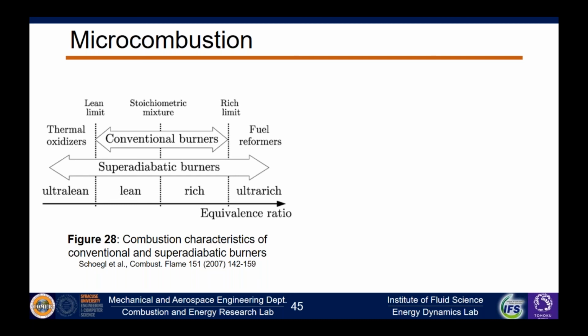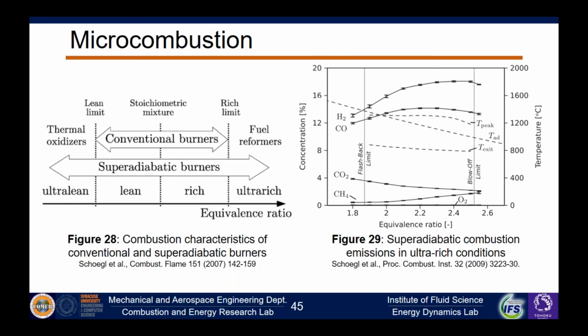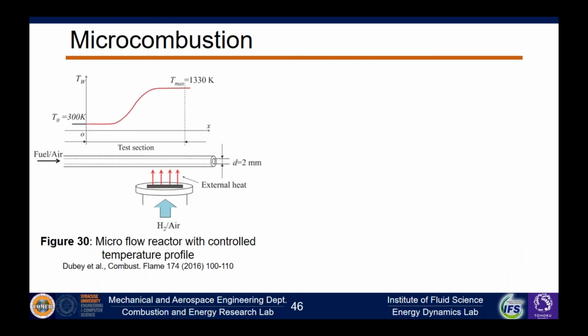Well, there's something called super adiabatic combustion, or super adiabatic burners. By recirculating the heat and using it to preheat the fuel and air, you can actually have enough thermal energy to sustain the reactions well beyond the upper flammability limit. That's the idea, at least. This is one example from Schoegl's group, who pushed the equivalence ratio well past 2. As you can see, hydrogen concentration is now significantly higher than what we achieved, as well as the carbon monoxide concentration. So if we can somehow push beyond that limit, maybe we can see a lot higher efficiency.